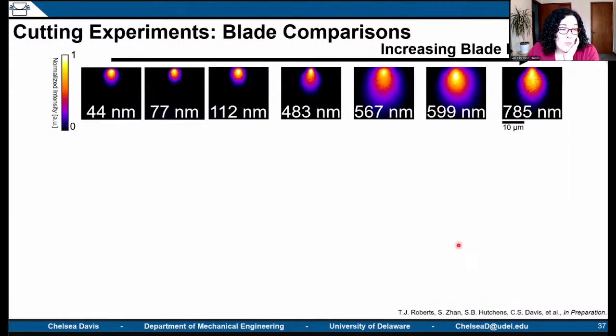And so then we went through and looked at the effects of how increasing blade radius changes the size and the shape of the large deformation zone ahead of this propagating crack tip. And these are the fluorescence intensity images of the activated mechanophore as we move from very sharp blades to very dull blades. And you can see there are larger and larger regions of activity as a function of how sharp or how dull the blade gets.